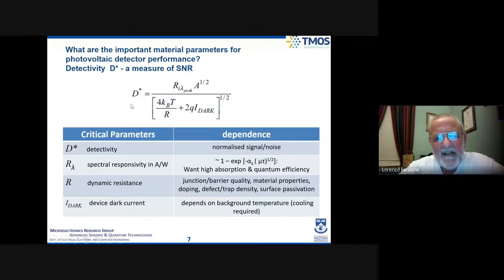So detector technology is all about increasing the responsivity, the signal, and reducing the noise, which is the dark current. And if you look at the responsivity, the signal, what you find is at a first order, it's proportional to this parameter alpha, which is the absorption coefficient.